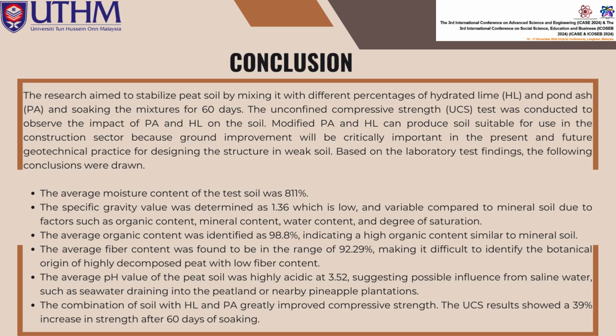The research aimed to stabilize peat soil by mixing it with varying percentages of hydrated lime and pond ash, then soaking the mixtures for 60 days. Unconfined compressive strength tests evaluated the effects of pond ash and hydrated lime. The following conclusions were drawn. The average moisture content was 811%. Specific gravity was 1.36, low due to factors like organic and water content. Organic content averaged 98.8% and fiber content was about 92.29%.